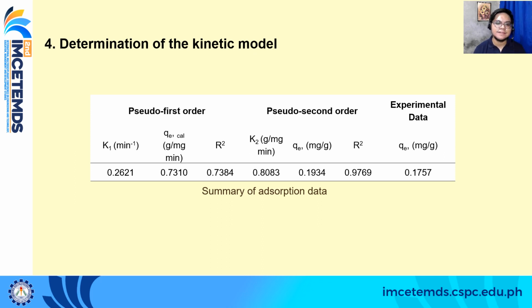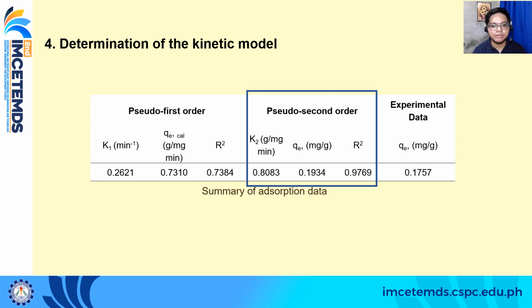Now from here, we can see that the pseudo second order, with the R squared value of 0.9769 and the adsorbed amount of 0.1934, adheres to the experimental data of 0.1757, and we can conclude that the entire kinetic data corresponds to the pseudo second order kinetic model. This indicates the applicability of the second order model to describe the adsorption kinetics of methylene blue dye using our iron oxide nanoparticles. So the best fit of the pseudo second order kinetic model proves that the mechanism of adsorption was chemisorption via electrostatic interactions or attractions.